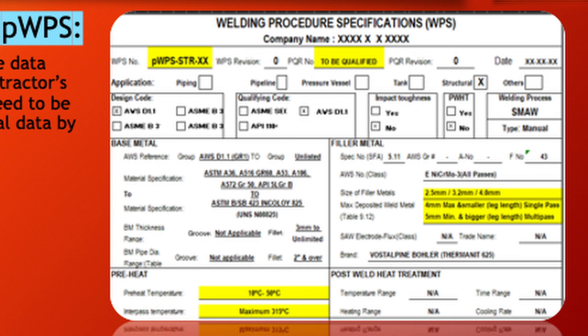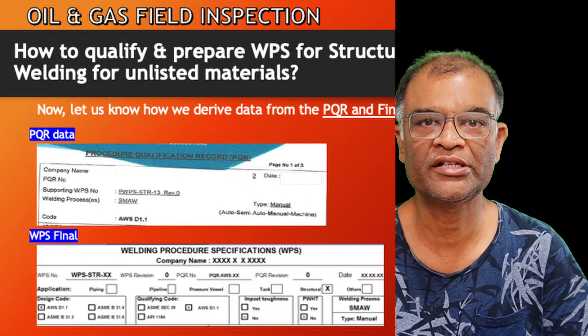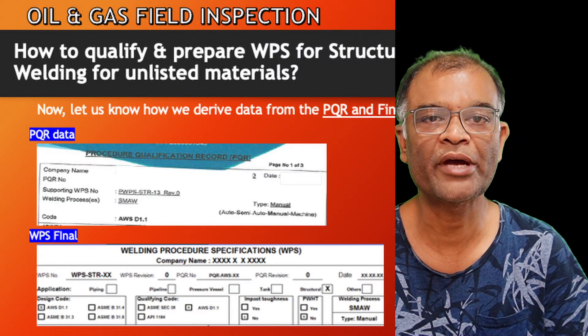We need to check the size of the filler material, the maximum deposited weld metal thickness based on the actual scenario, the preheat temperature, the interpass temperature, and the welding parameters — which are the most important portion where PQR results govern a WPS. Now we will learn how to incorporate PQR data and convert the pre-WPS into the final WPS.